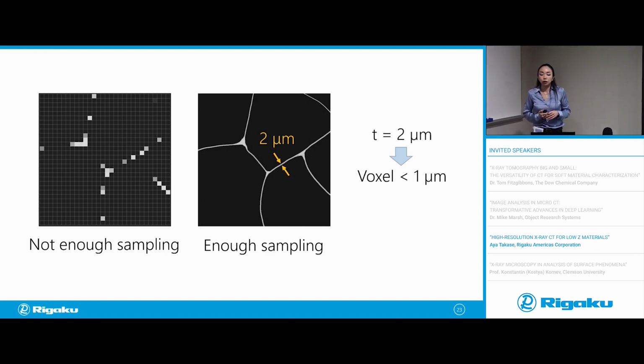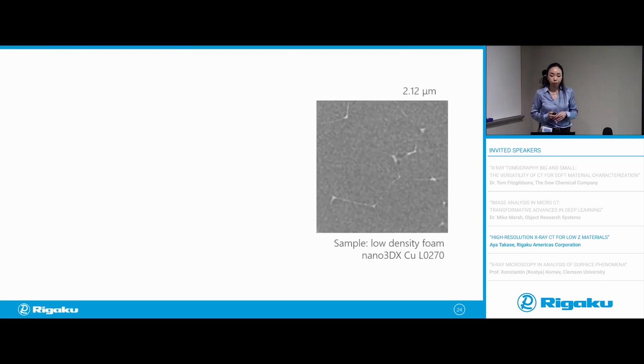Now, I would like to show you what happens if your sampling size or just general resolution is not enough. So this is a CT cross-section of a very low density foam material. And if you scan this sample with about 2 micron resolution, which is relatively high for X-ray CT, but obviously it's not high enough for this sample because we're supposed to see some cell walls in this foam. You can see a little bit of it, but not much of it.